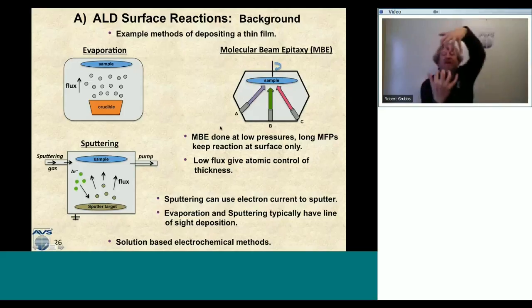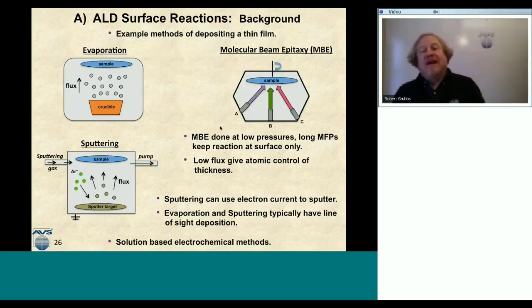The third technique is molecular beam epitaxy, and as you can imagine, this is an epitaxial technique where the atoms actually fit within registry of one another. And MBE is really done at very low pressures, because we want these long mean-free paths, because we want the reactions to happen only at the surface. We don't want them to happen in the gas phase. So we have these low pressures, these long mean-free paths,